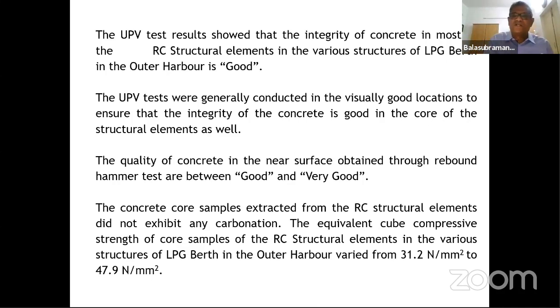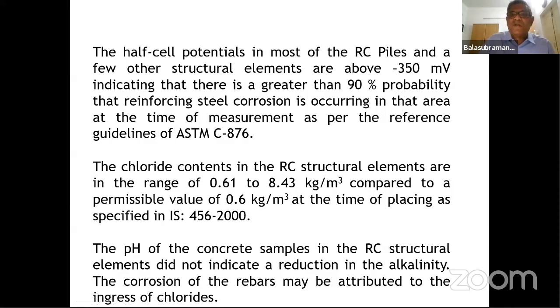I need to check the good locations also, because these are all very old structures, and in a marine environment where there's a lot of chloride. And the core tests were good, 31.2 to 47.9. So the designer gets a confidence. And half cell potential naturally will be more than minus 350 millivolt, even in good location, because it's chloride infested.